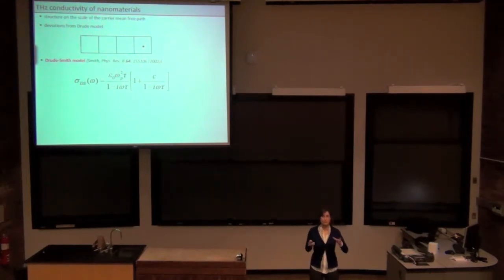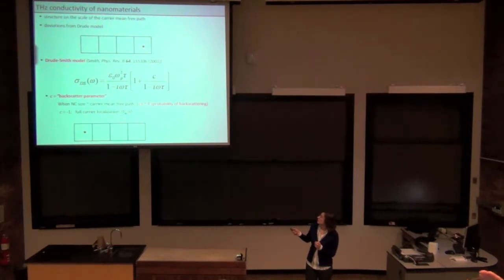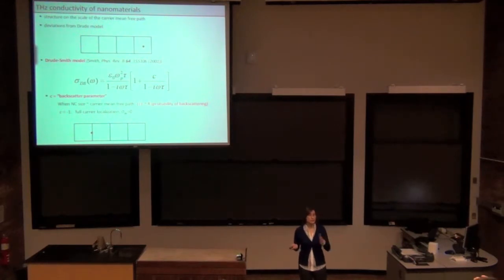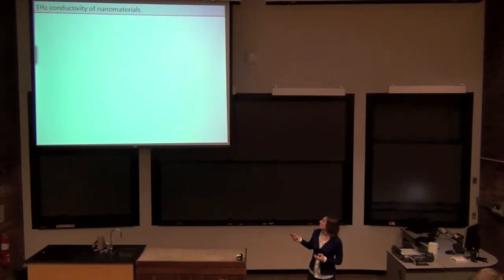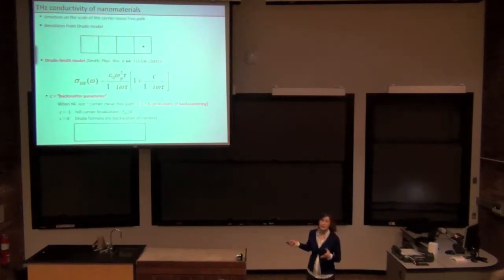and it varies from negative 1 to 0. At 0, you recover your normal Drude model. At negative 1, at zero frequency, the DC conductivity becomes 0. So this is where you have complete localization. In this case, your carrier is excited within one nanocrystal, let's say, and it cannot leave it. It just keeps bouncing from one hole to another. When C equals 0, the barriers disappear.